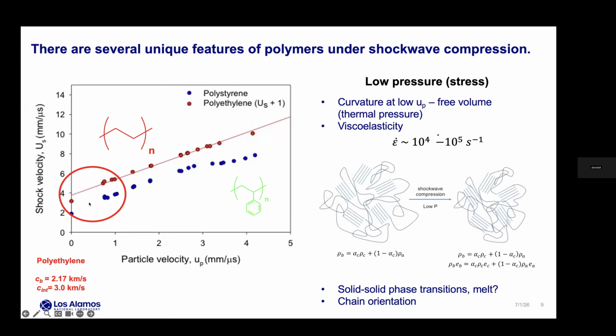So I introduced Hugoniot data in the shock velocity, particle velocity plane, talking to the historical data. I've selected two polymers to plot in this figure. This is the Hugoniot data for polyethylene in red, and polystyrene in blue. If you go back to this Carter and Marsh publication, the two things they discuss in detail are that cusp that I already talked about, and also the fact that at low pressures, unlike metals, the Hugoniot data does not extrapolate to the sound speed in the material.